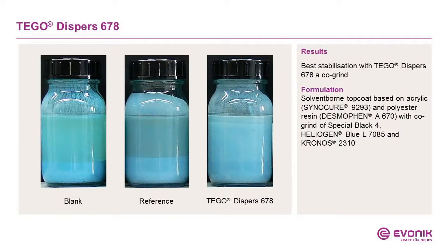Here an example what the TEGO Dispers 678 can do. You see it blank, so that means there's only the resin, only the grinding resin inside, or the letdown binder. Then in the middle it is a competitive additive, and then the TEGO Dispers 678 on the right side. You can see all pigments are stabilized very nicely and very smoothly, and it still looks very homogeneous.